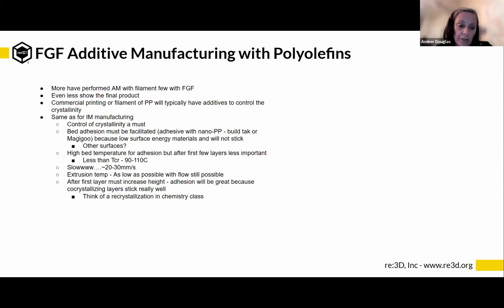And also, when you're extruding the first layer, you want it really close to the bed, but immediately after that, you need to raise it up because you don't want it to touch the molten layer below, because that's just agitating it. And that's essentially doubling up the amount of extrusion you have, because now the flow is doubling because you're going back and forth over the same molten polymer that already has been extruded, and it won't be successful.